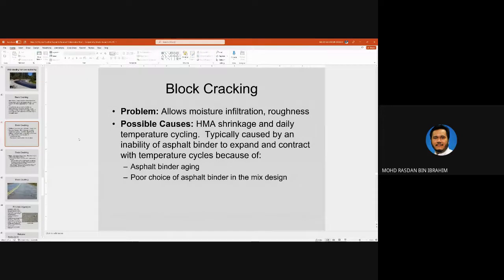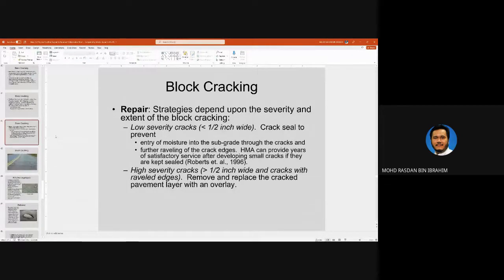for that pavement. So the repair strategies depend on whether the crack is not too big. If it is less than half an inch, you can crack seal the cracks, to prevent moisture traveling into the subgrade through the cracks, and further raveling of the crack edges. So you can stop it by sealing it with bitumen. So HMA can provide years of satisfactory service after developing small cracks if they are kept sealed. So this is very important. Once you notice it is cracking, you need to seal it very quickly before the moisture gets into the cracks. But if the cracks are larger than half an inch, you need to remove and replace the pavement layer with an overlay.